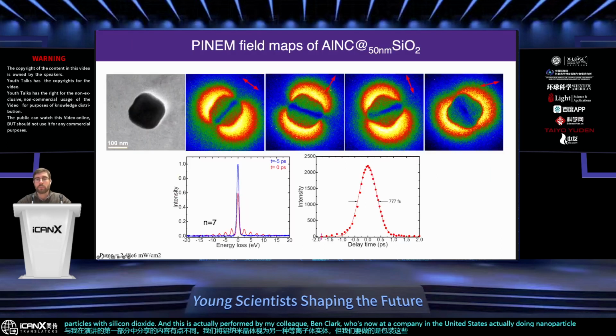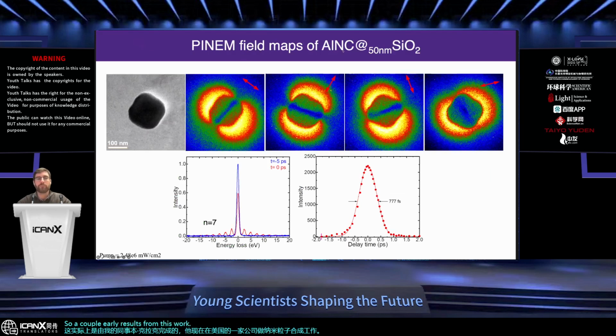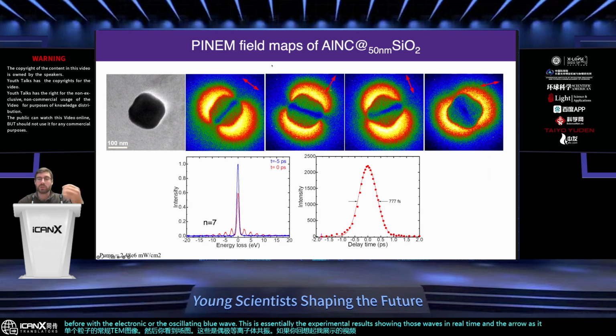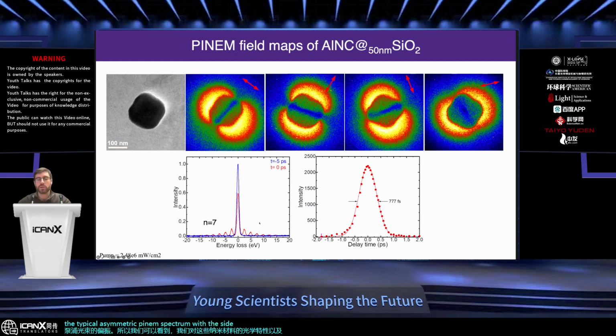A couple of early results from this work are PINEM field maps of the aluminum nanocrystals that are wrapped in the silicon dioxide. What we can do here is you have your regular TEM image of the individual particle, and then you see the field plots. So these are the dipolar plasmon resonances. If you think back to the video that I showed before with the oscillating blue wave, this is essentially the experimental result showing those waves in real time. And the arrow, as it rotates, is actually the polarization of the pump beam. So we can see that we have a polarization-dependent response to the optical properties of these nanomaterials, as well as the typical asymmetric PINEM spectrum with the sideband showing the energy exchange in these systems.